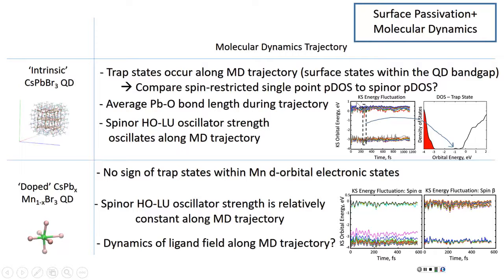And then the fluctuation. Which dynamics? Molecular dynamics, this picture which he's showing, adiabatic molecular dynamics, right? Yeah, we can skate by on that because the forces on the atoms aren't going to change drastically between spin orbit and spin restricted. So your electronic structure is not going to be the same if you did spin orbit. But it costs you nothing really to look, because you already have your dots showing. Take a look at the actual distribution of orbitals for this specific state, which is inside the gap. It doesn't matter, for the same reason you said, we're not expecting that the motion of ions will be affected by the spin case, right?